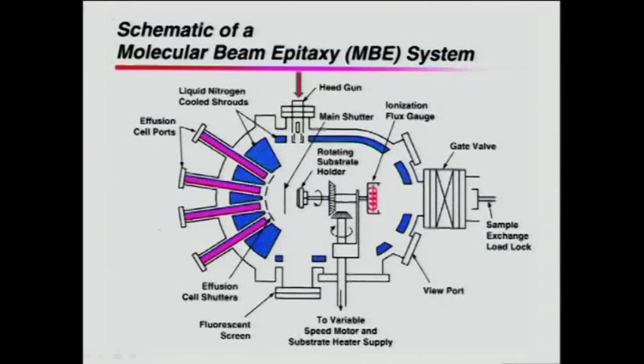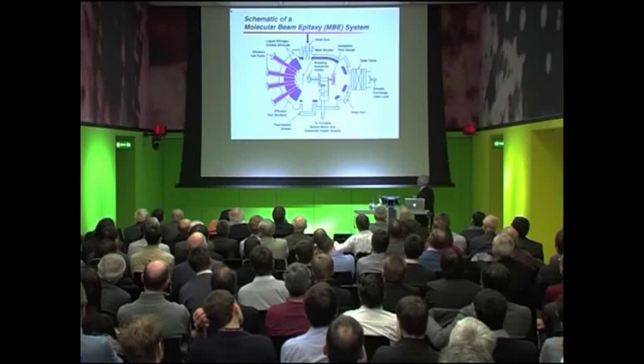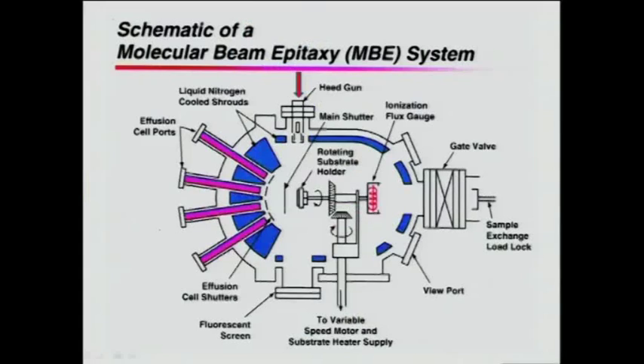I introduced in situ monitoring tools called a high-energy electron diffraction system. The electron beam impinges on the substrate surface during growth at a grazing angle, and the diffracted electrons are projected onto this fluorescent screen here. We look at the diffraction patterns of the surface. So we can look at the surface before we grow, as we dissolve the oxide from the surface, during growth, and then after the growth.